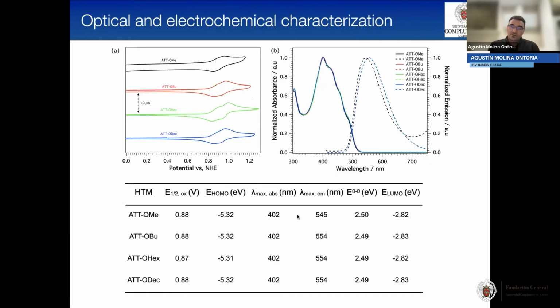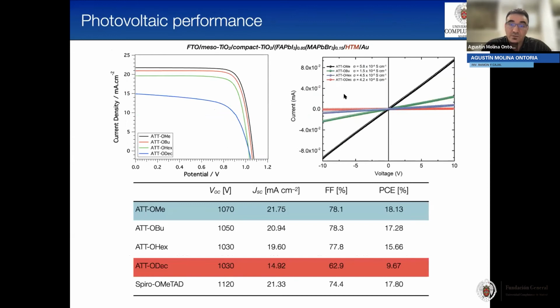But just introducing longer alkyl chains doesn't affect much the optical or the electrochemical properties. The big differences come when we talk about photovoltaic performance. So we can see here that the ATT methoxy, with the shorter alkyl chains, displays the highest efficiency, even higher than the spiro-OMeTAD. Upon increasing the length of the alkyl chains, the efficiency decreases. The conductivity of these hole transporting materials follows the photovoltaic trend. So we can see that the highest conductivity was found for the ATT methoxy, which is 2 orders of magnitude higher than the ATT with the longer alkyl chains.